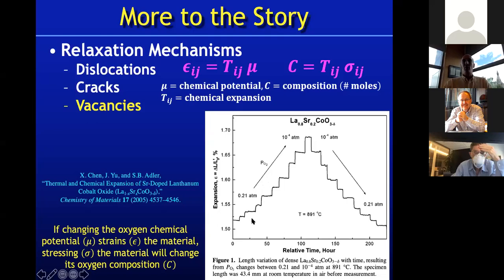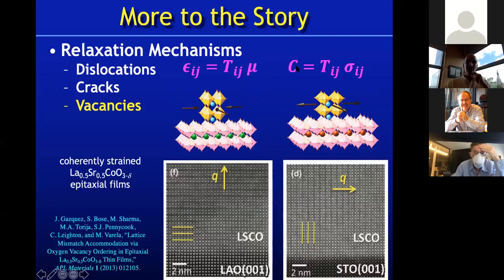What you can see is even though you're not doing anything, the thing is changing in size. So you see as you change the chemical potential, the material changes its size. So I can define a strain, some delta L of this rod, that accompanies this change in the chemical potential. Well, if changing the chemical potential strains the material, then I have to think about the converse effect, which thermodynamically must be the same property. This second rank tensor describes this property, relating stress to changing the oxygen composition of the material. And this is through oxygen vacancies.